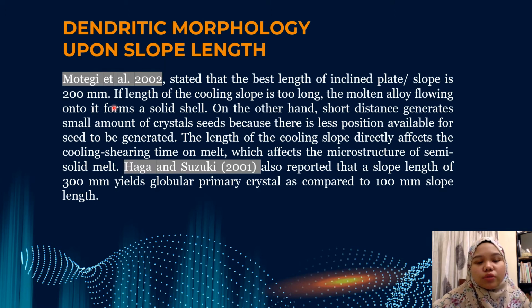If the length of the cooling slope is too long, the molten alloy flowing onto it forms a solid shell. On the other hand, a short distance generates a small amount of crystal seeds because there is less position available for seeds to be generated. The length of the cooling slope directly affects the cooling shearing time on the melt, which affects the microstructure of the semi-solid melt. Haga and Suzuki in 2001 also reported that a slope length of 300 mm yields globular primary crystal as compared to a 100 mm slope length.